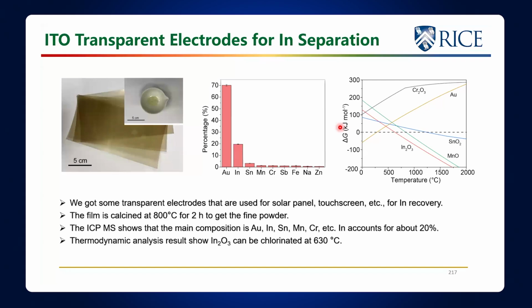Then you can plot calculations. These are just standard thermodynamic programs that you can buy, so you don't have to write the program. It will tell you at what temperature this should react with chlorine. When delta G is less than 0, the reaction is going to be spontaneous. And so you see that indium oxide would react with chlorine at somewhere around 630 degrees, right here. Gold is going to react below 250 degrees. This says that the gold should end up reacting, but it really is not going to react directly. The problem is that there's no stable gold chloride at atmospheric temperature and pressure.